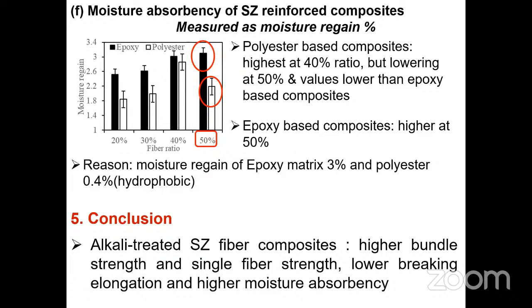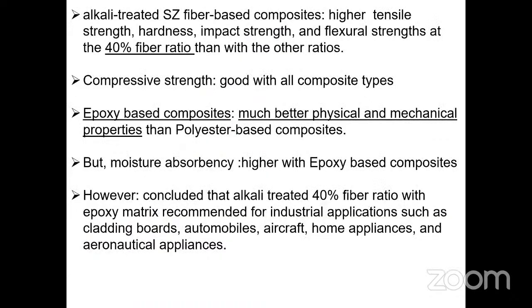The conclusion of this project is shown in this slide. Alkali treated Sansevieria fiber composite shows higher bundle strength and higher single fiber strength, lower break-in elongation and higher moisture absorbency. Alkali treated Sansevieria zeylanica fiber-based composite has higher tensile strength, hardness, impact strength and flexural strength at the 40% fiber ratio than with the other ratios.